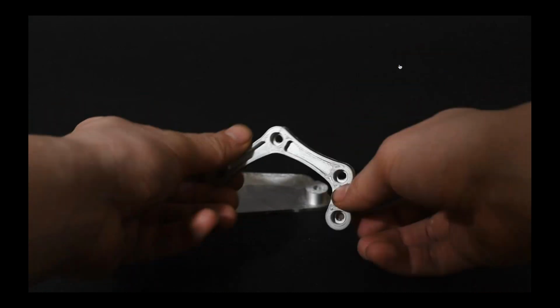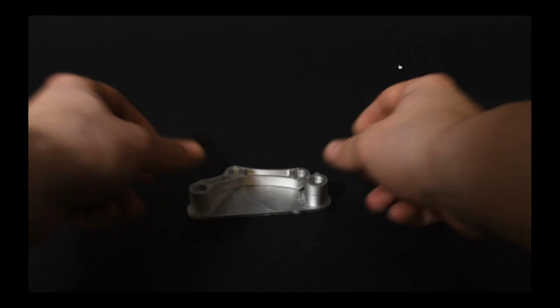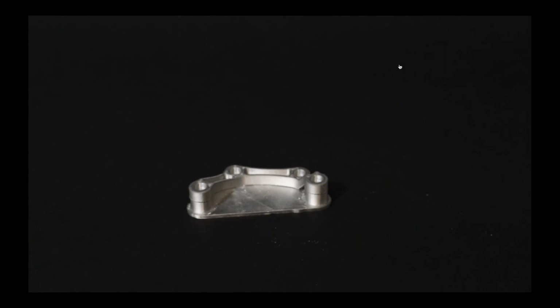This finished part is 17-4 stainless steel. Anything you can do to 17-4 stainless steel, you can do to this 3D printed part. Remember, we only hijacked the front end of metal injection molding. So instead of using an extruder and injecting the metal powder bound in a binder material, we use a high-precision hot glue gun to print your part. After that, everything's the same.